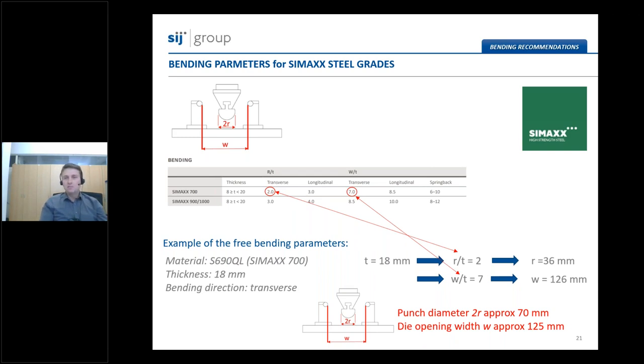If you are bending SIMAXX 700 grade with the plate thickness of 18 millimeters, so we can say that the bending direction will be in transverse to the rolling direction, and this is also called the easy way bend. So what we do first? First, you calculate the punch radius. You just multiply the thickness with the factor which is written in the table. So in this case, it is number 2. So the punch radius is 36 millimeters, resulting in diameter of approximately 70 millimeters.